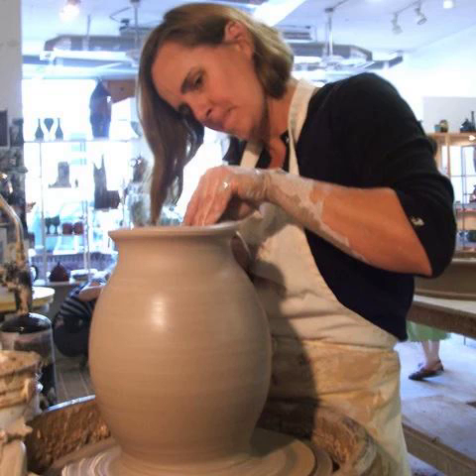And so you stir that glaze up, you apply it to the piece, and then you put a couple of other glazes on that piece, and it all matters: the application, the thickness, and then the temperature that the kiln fires to, the atmosphere in the kiln. There are a lot of variables that go together to make the surface of a piece.